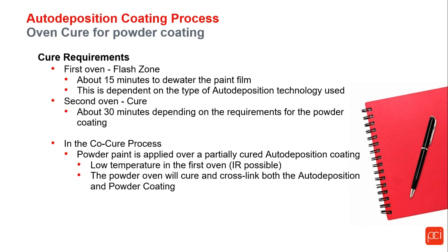And that is where the powder paint is applied over a partially cured auto-deposition layer. Low temperature in the first oven, and IR is possible there. And then in the powder oven, it will be heated to the required temperature for the powder coat. And the auto-deposition and the powder coating are both cured simultaneously in this oven.